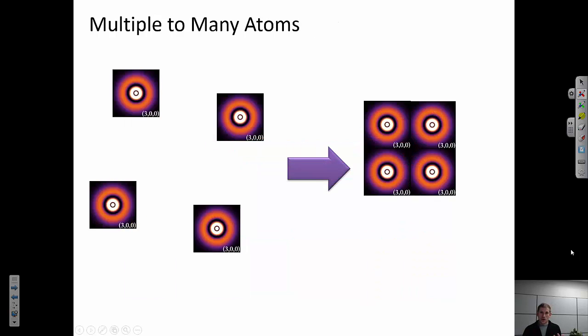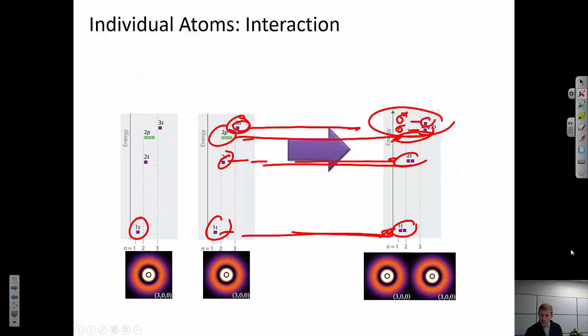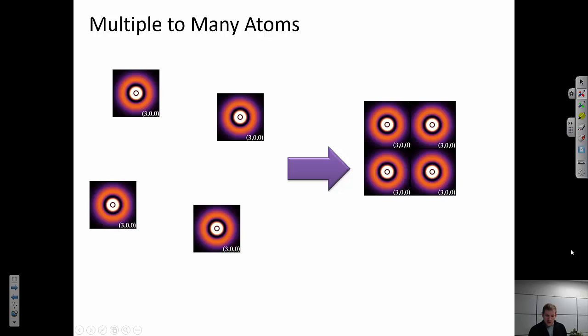What happens if I start combining more and more orbitals? So I'm going to really only focus on this higher-most energy level from here on out. All of these core-level orbitals don't interact and they don't change. Again, we start off with 3s orbitals. And we have four of them because we're combining four different atoms. When I bring those atoms together, when they start to interact, again, I'm going to have energy level splitting. And so now I can have four potential orbitals that electrons can fill.